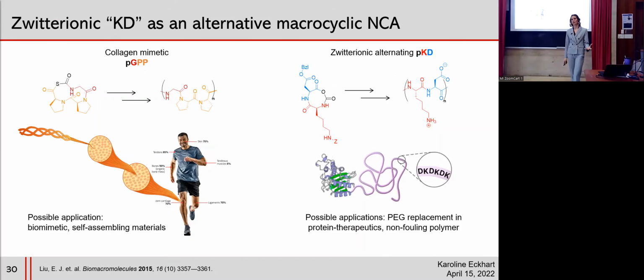And while we're still working towards creating this collagen mimetic macrocycle and polymerizing it, we wanted to shift our attention to a more synthetically accessible macrocycle. So we chose KD-NCA right here. The advantage of KD-NCA is that it's only a 2 amino acid sequence, which means it takes fewer steps to make the starting material. It only forms an 8-membered ring, which generally has less ring strain than an 11-membered ring that's bicyclic.